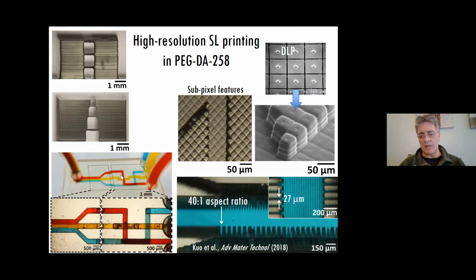stereolithography. And you can see here a variety of structures that these mixtures allowed us to create, such as single pixels. You can see this is the mirrors from the DLP. And then we had enough resolution, and the reaction was so fast that we could even see an image from the pixels. You could see the dimples from the pixels and then the marks from the mirrors. So that's what's given by that reaction.